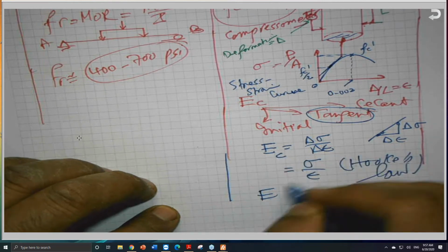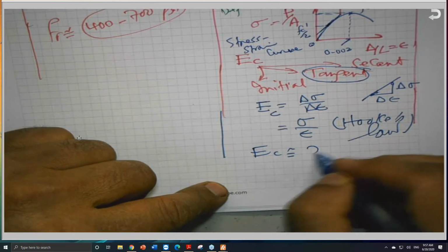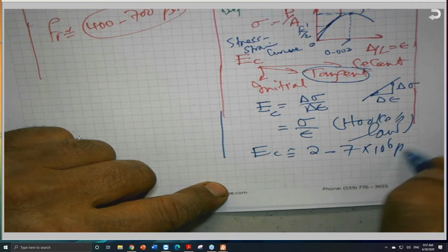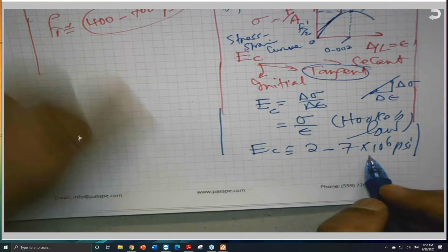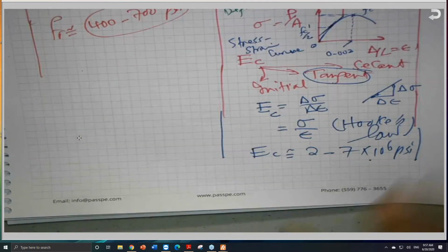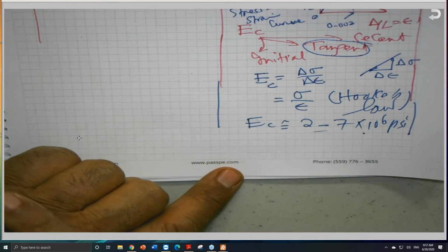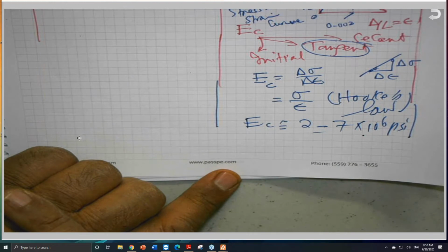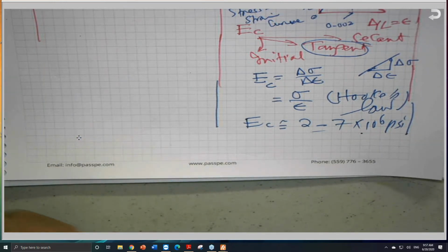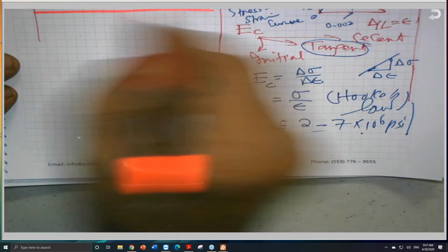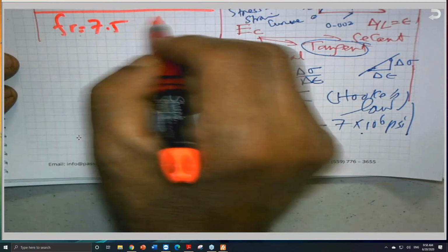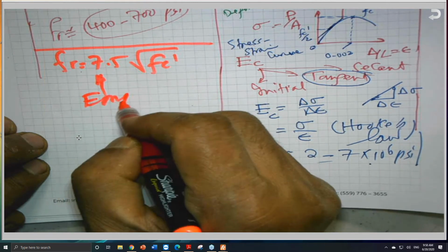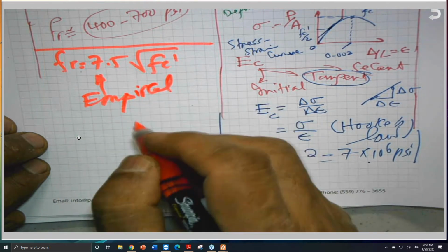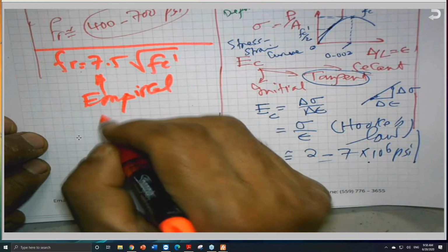But if you look at the modulus of elasticity, E sub C is between 2 to 7 million PSI. So the difference is huge. This is in millions, this is in hundreds, 400. So the modulus of elasticity is between 2 million to 7 million PSI. It depends on f'c. They have an empirical formula here, the one I mentioned. F sub R is equal to 7.5 times the square root of f'c. This is an empirical formula.